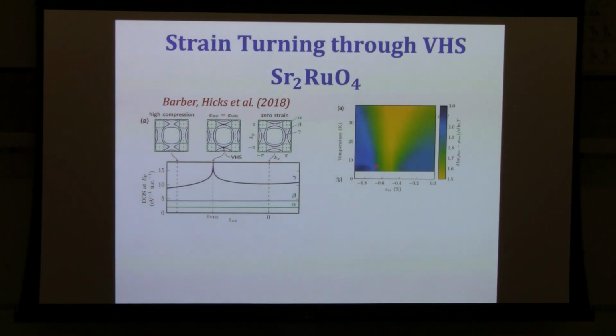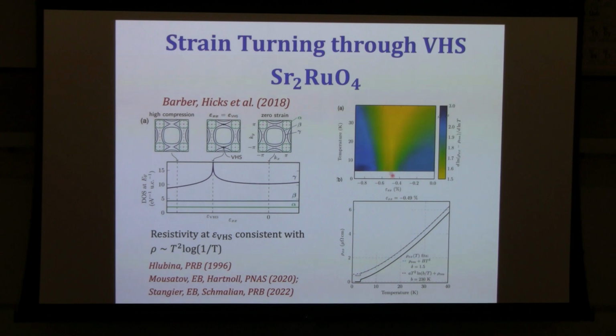But here the quantum critical point is actually very simple. It's just this topological transition of the Fermi surface. This is all that's going on here. Moreover, it's been measured. This is the resistivity as a function of temperature at the critical strain, and you can fit it to a power law. If you try to do that, the power is close to 1.5, but it fits equally well to this form of T squared times log of 1 over T.